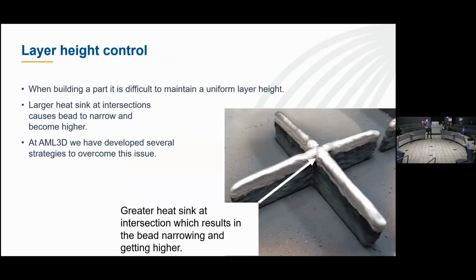One of the key things for getting the process to work is that you have this problem with layer height control. So when you start manufacturing parts, for example, you end up with a much greater heat sink, and so your bead shape changes completely. Okay? So it ends up being much narrower and much higher. And so if you didn't do anything, what you'd end up with is a massive hump in the middle, and everything around it is much lower. And so one of the key bits of the technology that we've developed is to get around that problem.